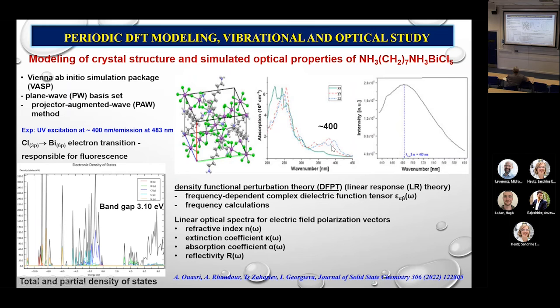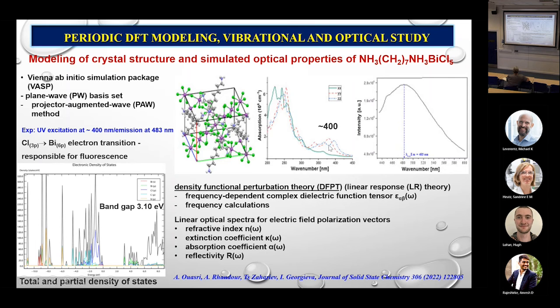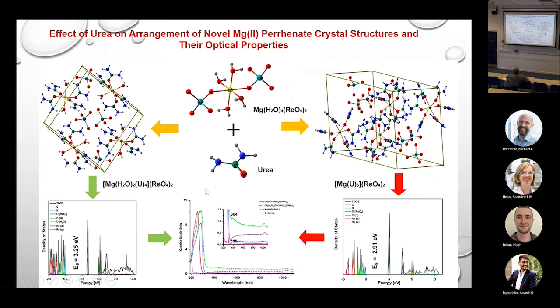So this is very good. Our calculated absorption spectrum agrees very well with the experiment. And we also calculated the band gap, in good relation to the long wavelength absorption. When we calculate the total and partial density of states, we can estimate the character of the electron transition, which finally is responsible for the fluorescence of this heptamethylene diammonium bismuth pentachloride, and then we apply the same approach to another object.